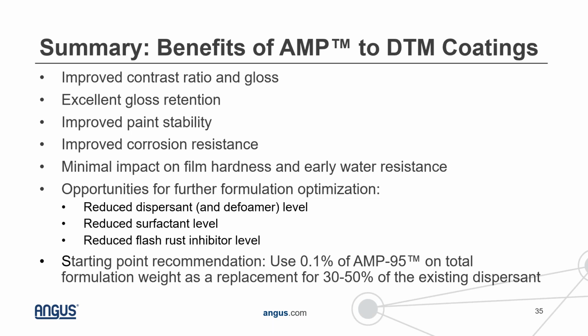And so based on this data set that we have, our starting point recommendation will be to use 0.1% of AMP95 on total formulation weight. And you can use that to replace 30 to 50% of the existing dispersant. And that should yield some improvements to a lot of these coating properties that are really critical to waterborne industrial coatings.